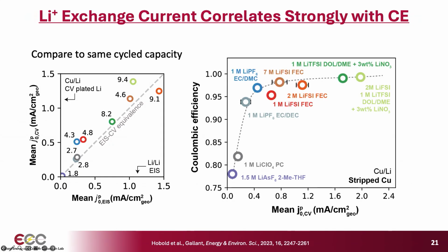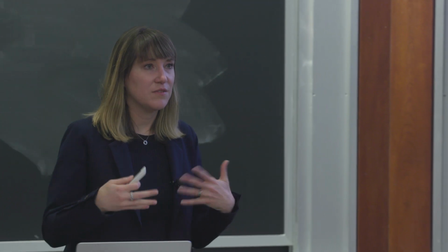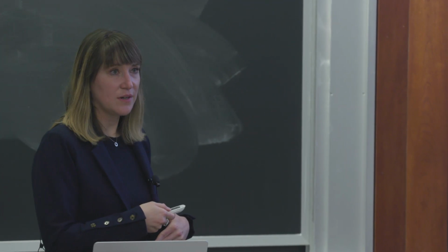And now we can look at how the exchange current density relates to Coulombic efficiency. As shown here, you see a pretty clear positive correlation between the 2. So in other words, SEI that support high reversibility are also SEI that facilitate high lithium exchange rates.